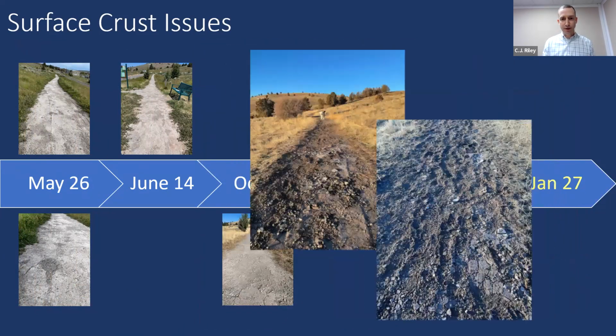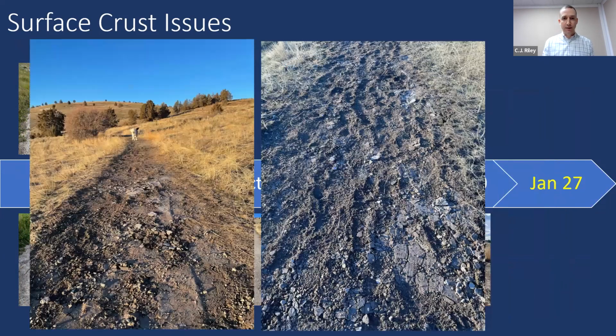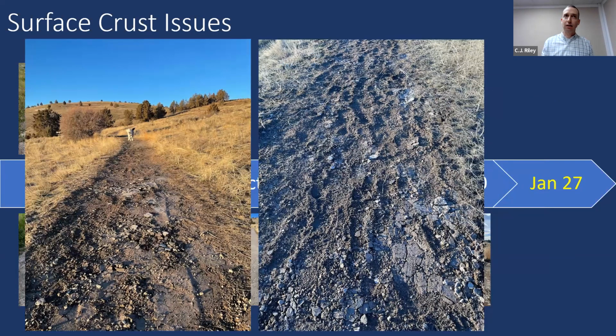And then still farther into the winter, a lot of the soils here are also expansive in nature. So if they go through wetting and drying cycles, they tend to fluff. And so it's pretty clear that there are some challenges with this location, with this binder, and it's not quite right.